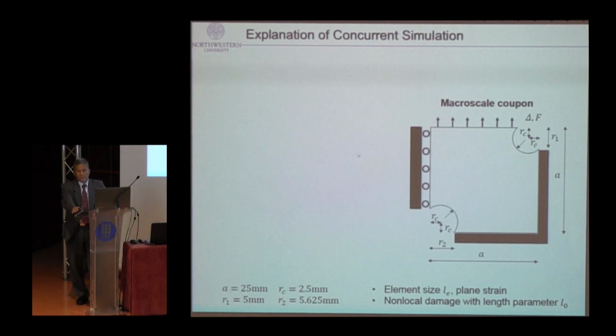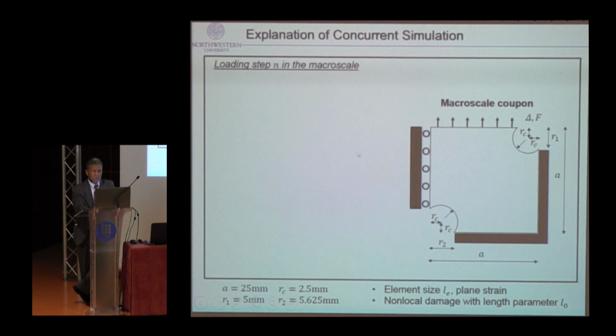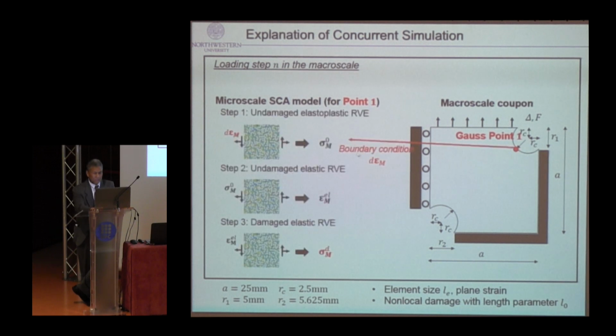We borrowed the idea from FE square, the finite element square technique. So basically, this is a macroscopic response, and we discretize it with lots of Gauss points. Okay? And I'm going to loop on the step, and at each Gauss point, I compute the microscale. But for solving the problem, I need to break it down into three steps, and then I take a homogenization scale and feed it back to here. So that's one computation. But this one can be pretty large.